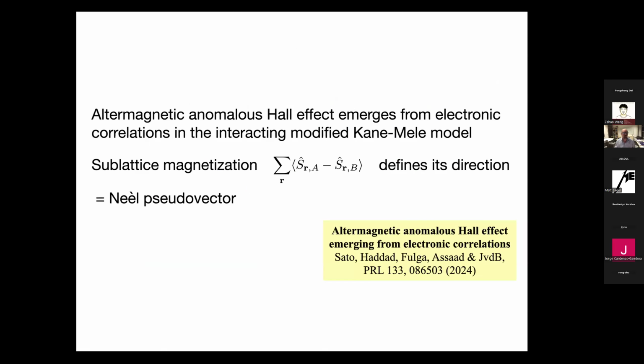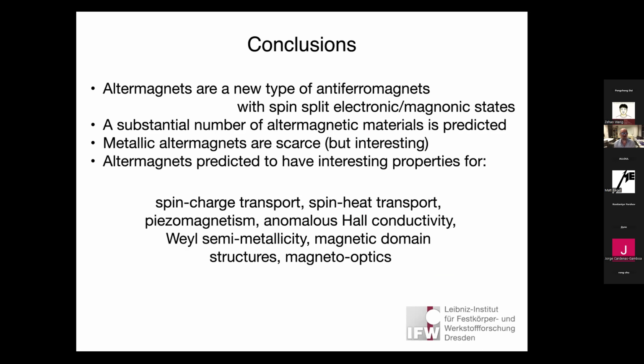Okay, why? The altermagnetic anomalous Hall effect emerges from the electronic correlations in this interacting Kane-Mele model. And where is my thumb pointing? Well, the thumb is pointing along the direction of the sublattice magnetization. This is the third direction. So it's the spin on the A sublattice minus the spin on the B sublattice. And that defines the direction that in turn defines the anomalous Hall effect. So then it's the Néel pseudovector that takes the role of magnetization, or the role of magnetic field, for this altermagnet.